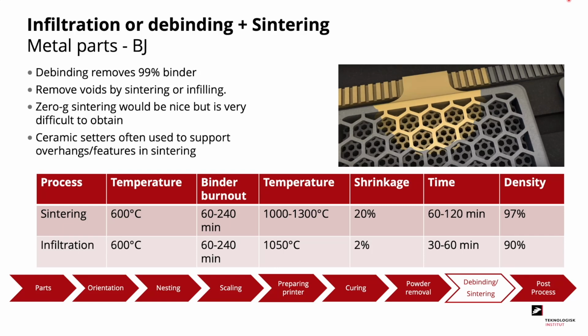Below you can see some typical temperatures and times for both sintering and infiltration. So first you have the binder burnout process, and then you have a sintering or infiltration step. In the sintering step you typically have 20% shrinkage but a very high density, while in the infiltration step you only have 2% shrinkage, but you also end up with a lower density.